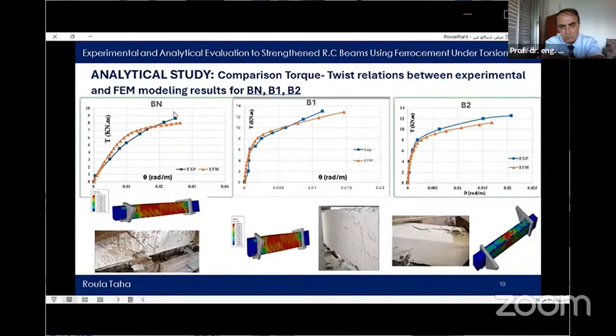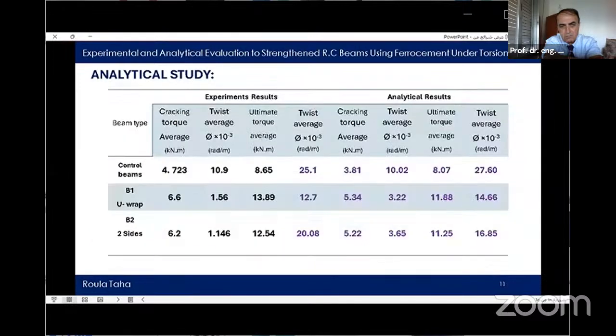In the same manner, we can see that the failure mode of the experimental and analytical curves of the B1 beam is close. Also, the cracks were observed at the midspan of the beam in both cases, despite a slight decrease in the experimental twist angle. The torsional behavior of both experimental and analytical tests of the B2 group is comparable. The analytical curve slightly diverges from the experimental one.